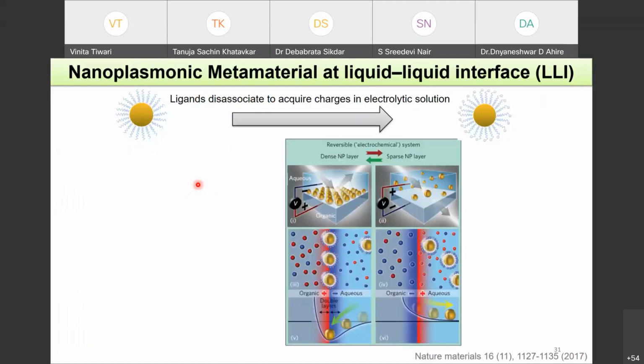That is not electrotunable. So let us try to make a reversible system where you can use electrodes in the aqueous and organic phase. The organic phase is the oil phase, the aqueous phase is the water phase, and the nanoparticles have negative charge. So if the electrode in the water phase has negative polarity, you are basically pushing all the nanoparticles toward the interface where they will populate the interface and form a dense layer. So this is the case where the interface will behave like a mirror.